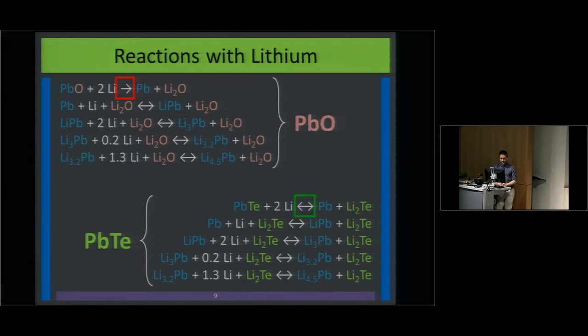The last 4 reactions for each are pretty much the same. That's just your lithium insertion into lead, and that's how you get your ultimate 4.5 lithiums per lead atom. One thing to notice is that while that reaction is taking place for each set of reactions, you have lithium oxide or lithium telluride present. So once you convert that oxide or telluride to lithium oxide or lithium telluride, they stay for the rest of the lead insertion reactions.